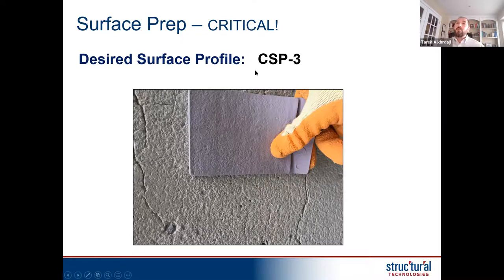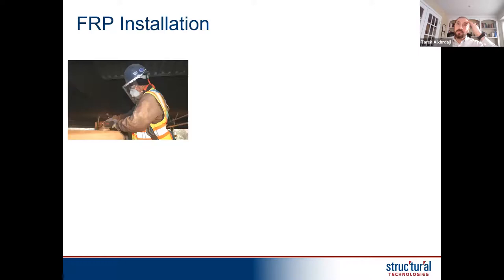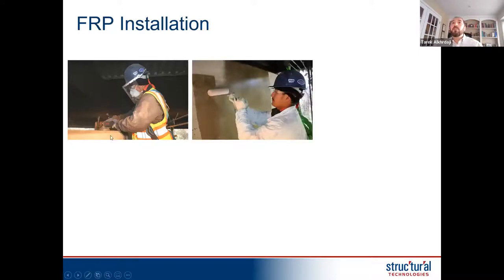The surface roughness we try to target when we install FRP is referred to as CSP3, concrete surface profile number 3. This is a classification developed by the ICRI, International Concrete Repair Institute. And by having a number for quality control, it gives us an idea of the minimum surface, and an inspector can verify it before the FRP is installed. Once you do the grinding and open the pores of the concrete, you can see this pier, for example, is a bridge pier. It looked normal, but once you grind it, you can see all these bug holes and micro cracks.